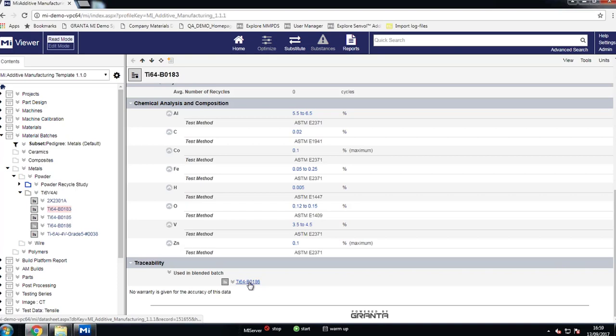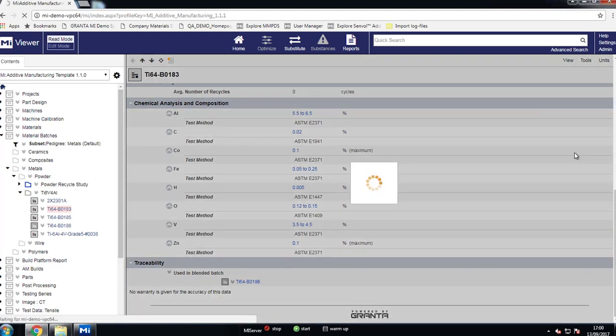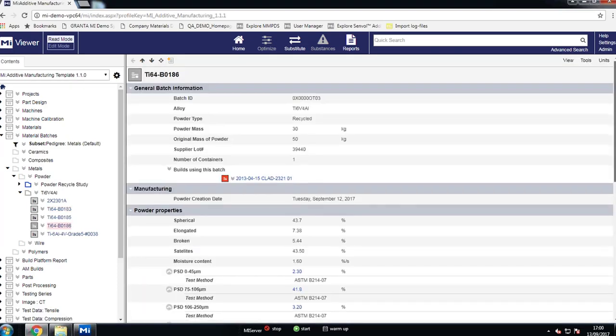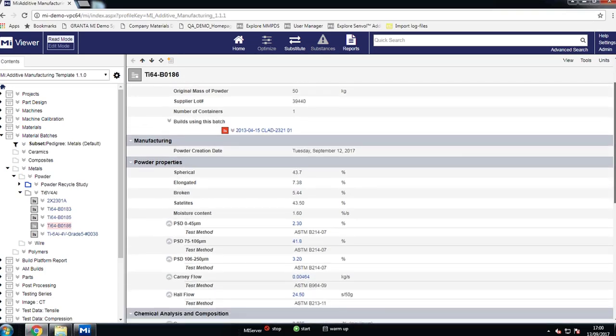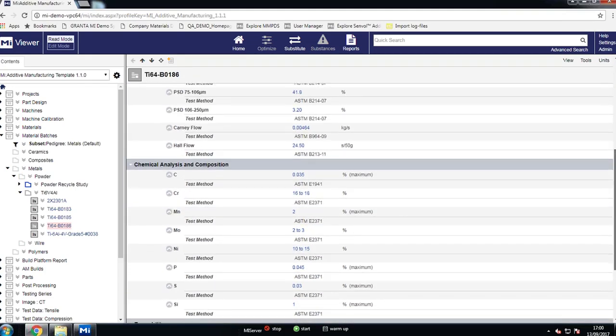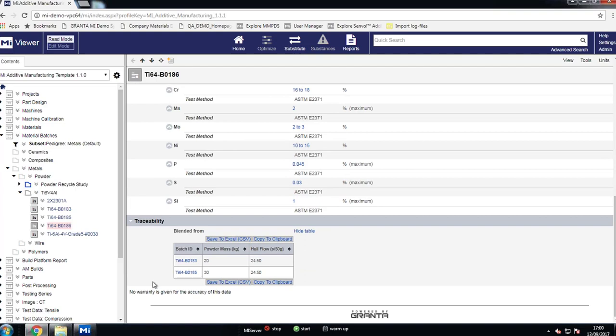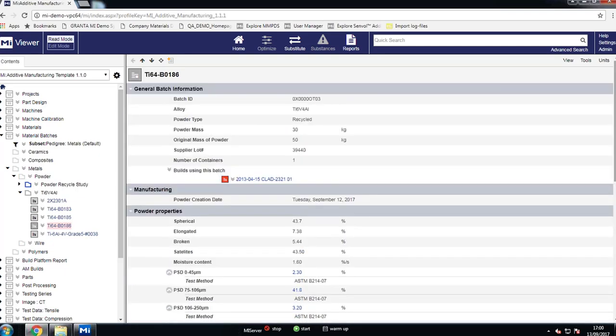Now we can also capture blended powder materials, which is done quite often. So here you can see the powder properties and chemical analysis for these two different batches of powder that were blended together. And it's very important to keep traceability of your information. So from powders, you can follow all the builds that were manufactured using that powder.